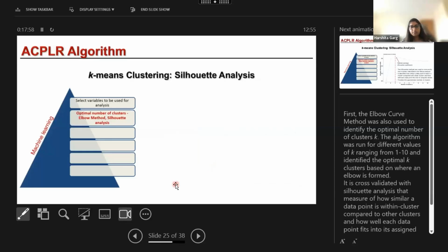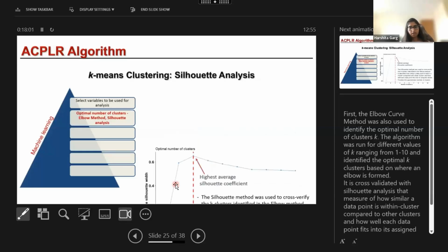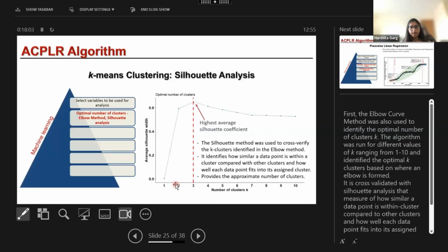Now to cross-validate it, we use a second method of clustering called silhouette analysis. This method identifies how similar a data point is within the cluster compared with other clusters, and how well each data point fits into the assigned cluster. So based on this, the highest silhouette coefficient gives the number of clusters required. Keep that in mind: it is not the correct number of clusters. It is only the optimal number of clusters, not the exact number of clusters that could be identified.